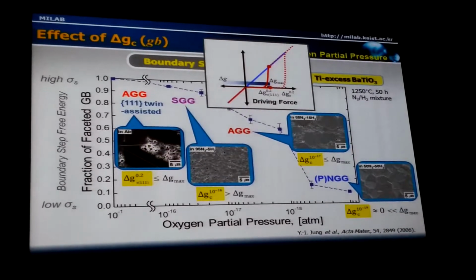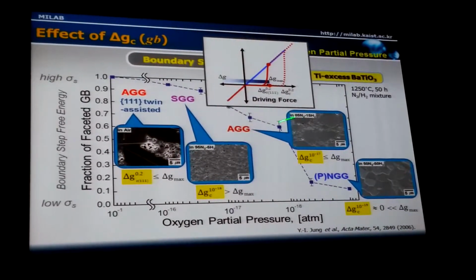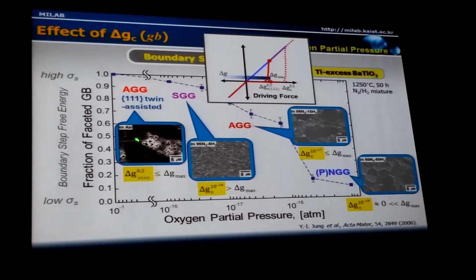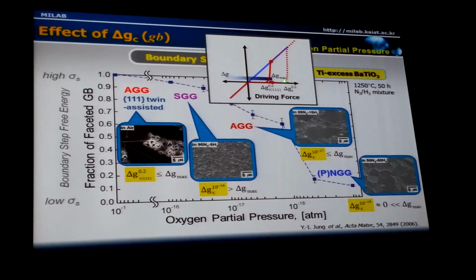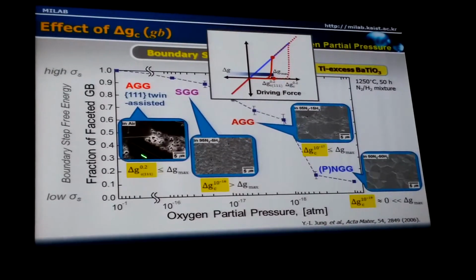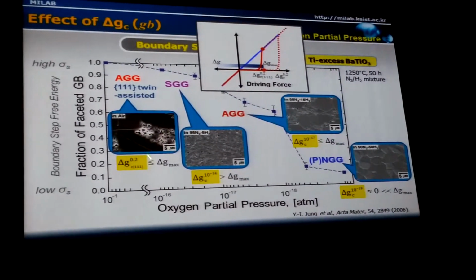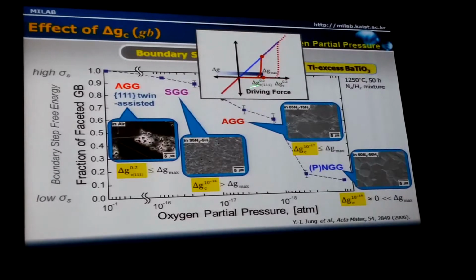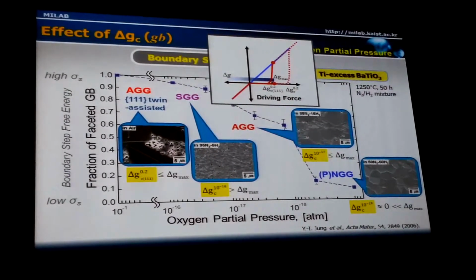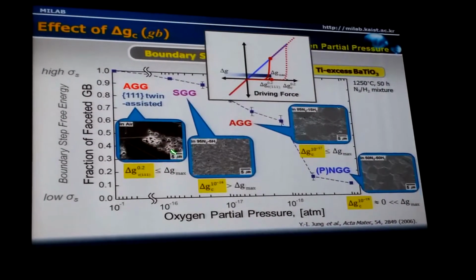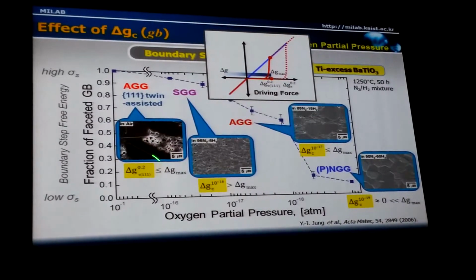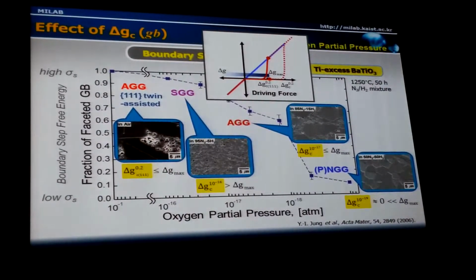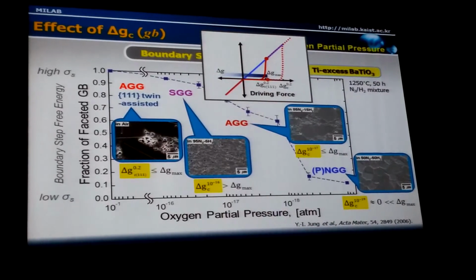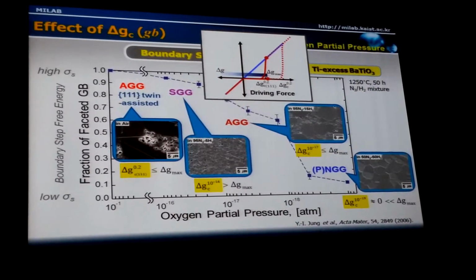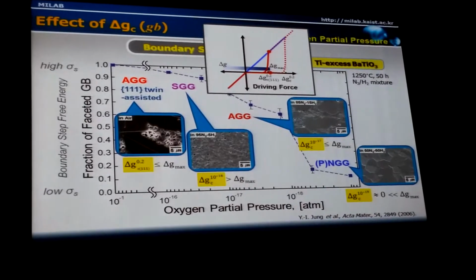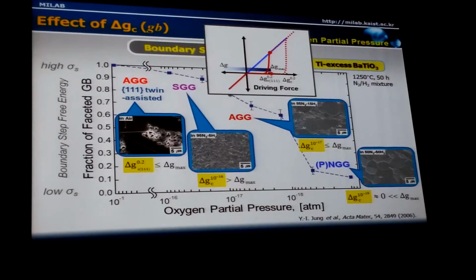And with the increase of oxygen partial pressure comes the formation of {111} twins. Although the maximum driving force increased further because of the presence of {111} twins, the critical driving force for grain growth is reduced because twin-assisted grain growth occurred, and because of that, big abnormal grains that contain {111} twins form. So all these experimental observations support our prediction based on the mixed control of boundary migration grain growth.